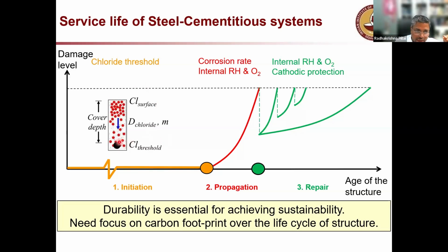When the chloride starts getting at the steel reinforcement, it gets deposited on the steel surface. And when that concentration reaches a value which we call chloride threshold, then the steel starts corroding. So this is the point when that steel starts corroding. In the time scale, the horizontal axis here is the time axis. Vertical axis here is the damage level. So until the corrosion of steel starts, you don't see any damage. Okay. Corrosion induced damage is our focus today.